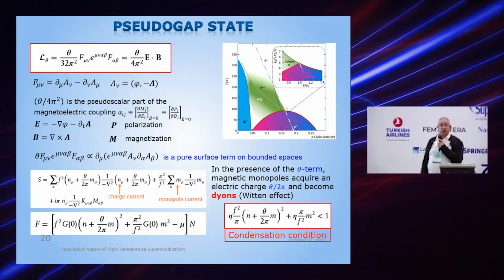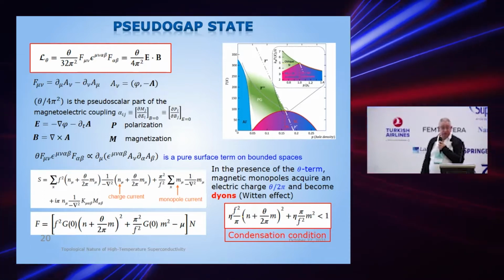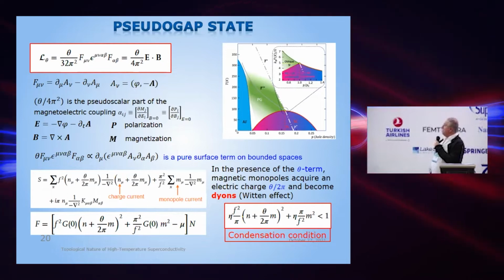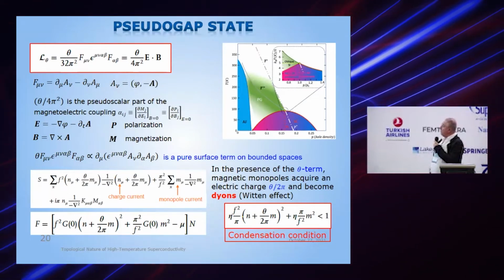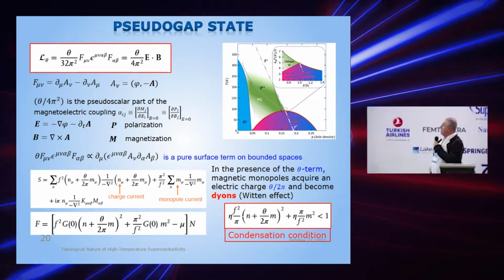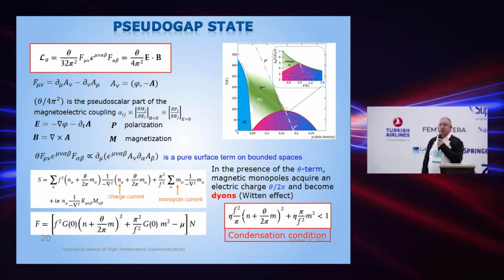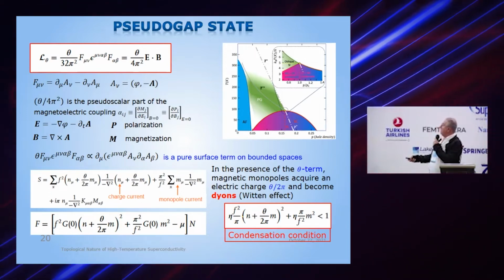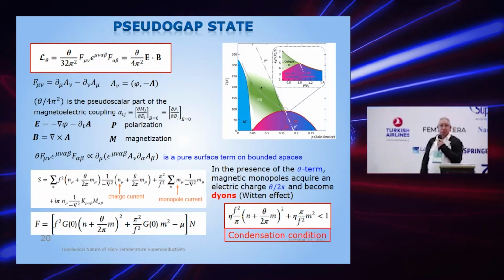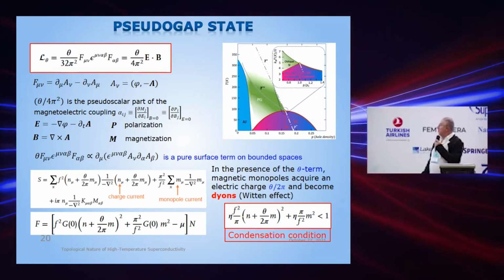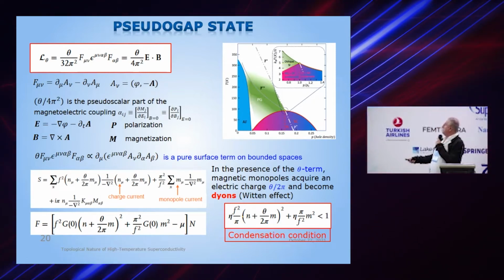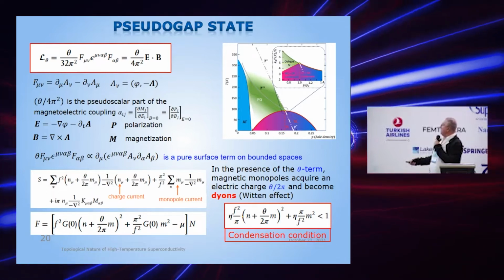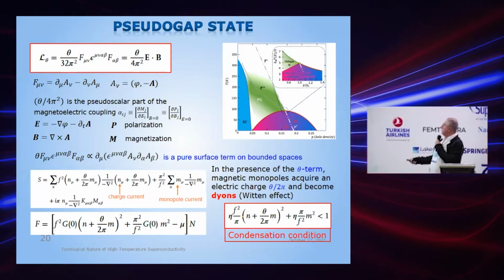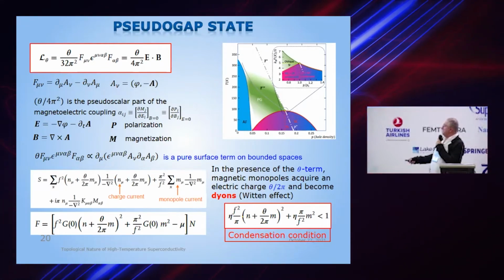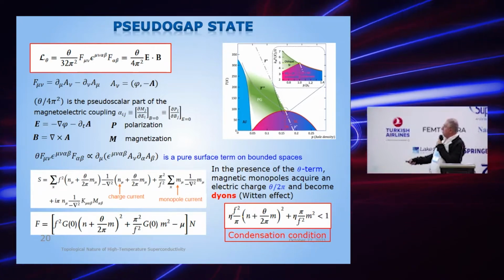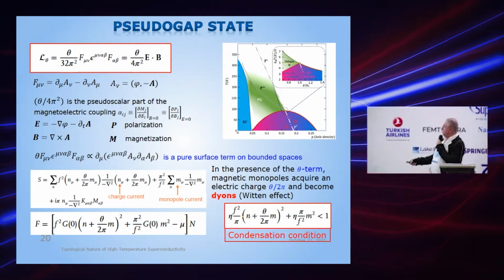And then if we just integrate out all the gauge fields and find out what is the action and then the free energy of our oblique superinsulator state, we find out that within this state, there are two kinds of carriers. One of them are dyons, the particles which carry both magnetic and electric charges. Another term which presents in this action and then in this free energy is the monopole current. And then we have this free energy where we have the term of dyons and terms thanks to monopoles.